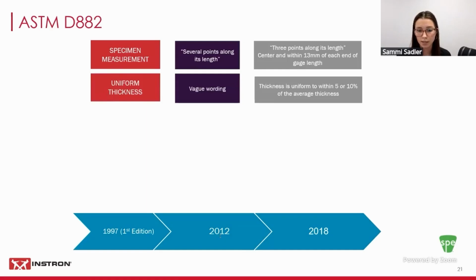Another change is that subsection 7.5 has now been updated to state that the specimen must be within 10% uniformity of the thickness based on the average thickness, whereas originally there was very vague wording around how thick your material must be.